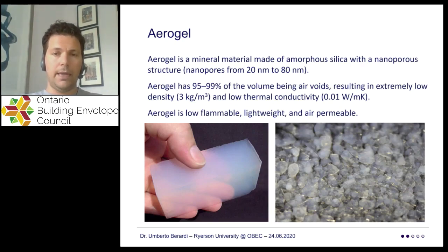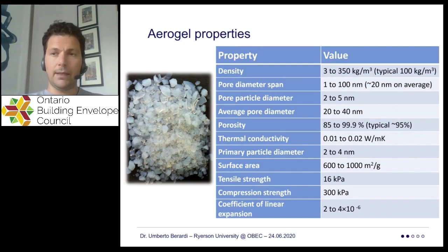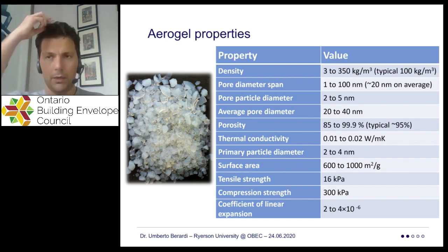An aerogel is basically a material in which you try to eliminate all the liquid portion from a gel. They are often described as frozen smoke because in reality they look like frozen smoke. These are very lightweight materials. They weigh only a few kilos for an entire cubic meter. They have 95 to 99 percent voids, and they have a low thermal conductivity of only 0.01. How you typically obtain these characteristics is by a chemistry process, which unfortunately makes this product quite expensive. This process starts from a silica gel, very similar to the gel you may be using in your air.